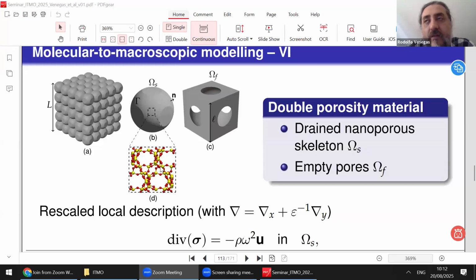If the standard deviation is not too high, obviously. So if you have one type of material with a unimodal pore distribution with just one type of pore, and you compare its permeability with the permeability of some material that has a narrow distribution of pores centered at the other value, then the permeability wouldn't be that different. So it's got some influence, sometimes higher, sometimes smaller, but it wouldn't change the macroscopic form of the equations. That's the key message we had.